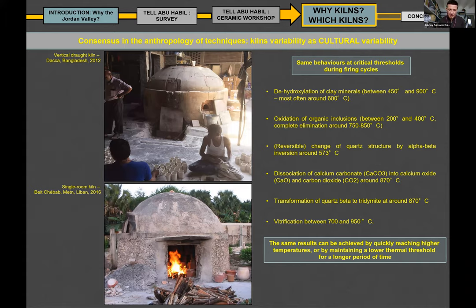way by limiting this notion of performance to some decisive passages, decisive thresholds, and physico-chemical transformations happening during the firing cycles. For instance, the dehydroxylation. The dehydroxylation is the process of the last disappearance of very little remains of humidity, of water, within the molecular structure of the clay. This process happens around 600 degrees during the firing cycles, but there are also several other very characteristic physicochemical transformations, like the structural change of quartz, the dissociation of calcium carbonate, vitrification, and so on.